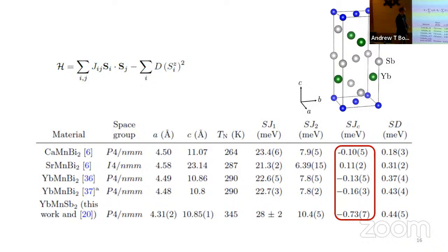Why is it so much different? We don't know the answer for sure, but one possibility is there may be different contributions to the magnetic coupling between these atoms that involve these intermediate orbitals. So there could be some sort of antiferromagnetic super exchange, which tends to cause antiparallel alignment of spins. And that could be competing with some kind of metallic exchange, which involves the electrons on these antimony orbitals, which is where the conduction band is largely located in real space.